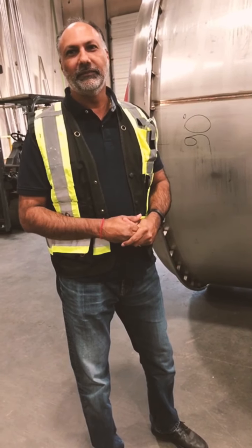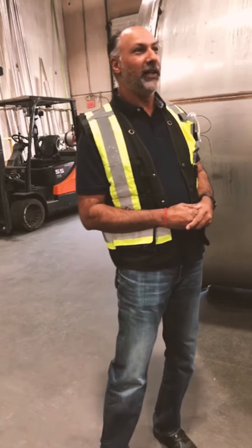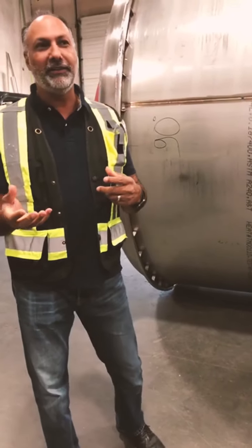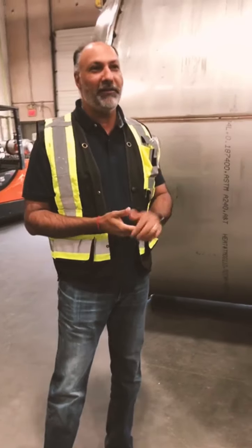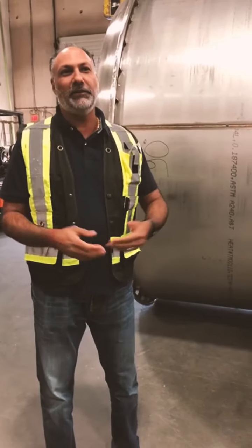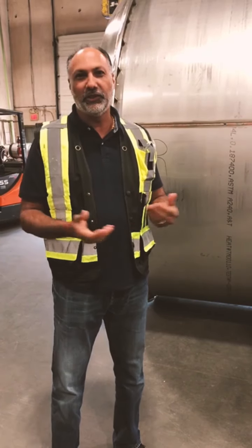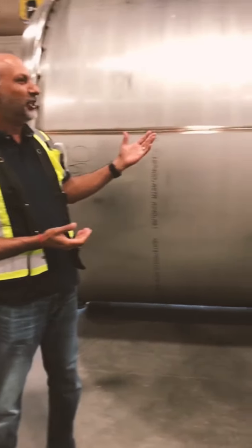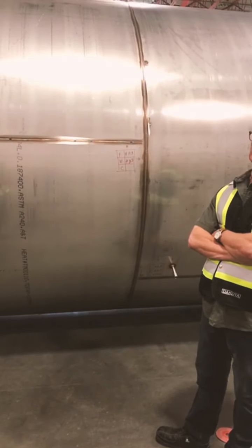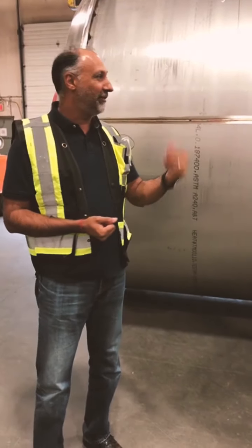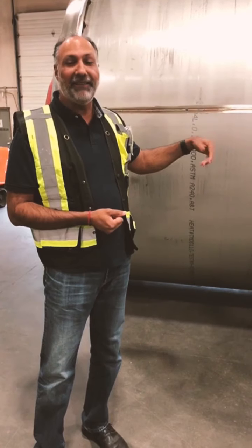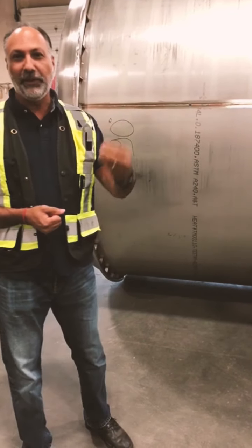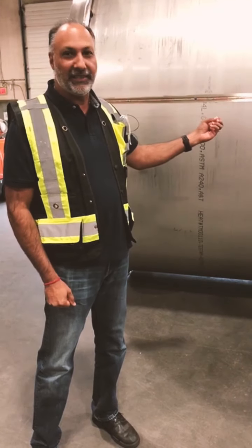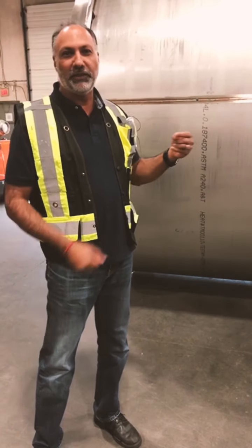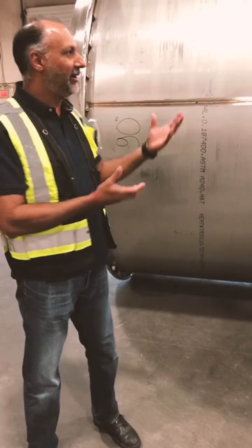What can an inadequate weld mean for a brewery? An inadequate weld, I mean, it depends on what kind of inadequacy. If you have, let's say, porosity, in any case it would mean premature failure would be the quick answer. Especially on a pressure vessel, because this is very structural in the sense that we want to make sure it can handle the pressure. So whether it's undercut or slag, which usually doesn't happen in a TIG weld, you can have excessive heat and have burn through. And that burn through, because you're basically burning away some of the chromium in the stainless steel, can actually create rusting, because you burnt away some of the protective elements that are inherent in this material.